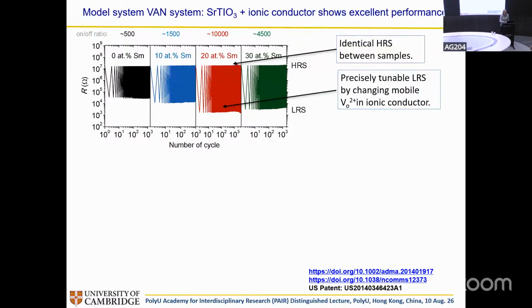So we were able to show that if you look at the resistance versus the number of cycles, so this is switching this thing on and off, the voltage switching up and down, you can see that the high resistance state always stayed the same, no matter what the composition of the ionic conducting electrolyte is. And the low resistance state could be tuned, and that low resistance state is precisely tunable by changing the mobile oxygen vacancy concentration in the ionic conductor. It goes this way, then it goes that way, because as you put lots of vacancies in, they start to coalesce, and so they're less mobile. And this is exactly in line with the ionic conductivity. So that was very nice. We could see you really need to control the vacancy concentration. The switching process occurs by those vacancies changing the Schottky barrier height at the electrode. And so that's what you have.